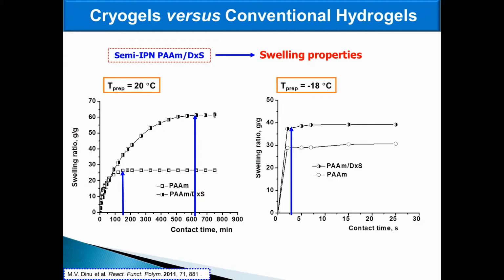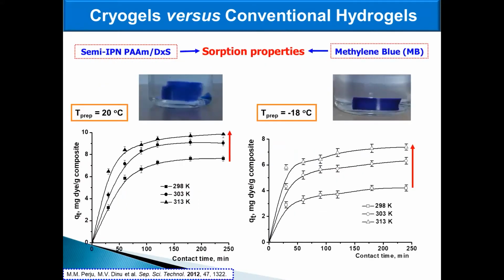When gels were prepared by cryogelation, the time necessary to reach the equilibrium swelling in water was in the order of a few seconds, while the conventional ones needed hundreds of minutes. The superfast swelling of cryogels is explained by the formation of a macroporous structure with interconnected pores which allowed the fast diffusion of water within the polymer network.